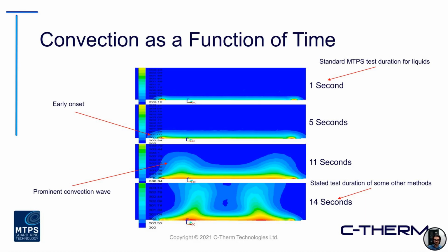If you were to increase the test time, and you can see this in the simulation that was performed at about 5 seconds, 11 seconds, you start to see more and more of that convection wave build. And then when you're analyzing on the upper end of around 14 seconds, which granted isn't that long of a test time, you do notice quite large convection errors that can be introduced. And if you look in the literature and standards for other methods that deal with liquids, some of them state test times even longer than this. So it's something that you really need to take into account when you're designing your testing setups.